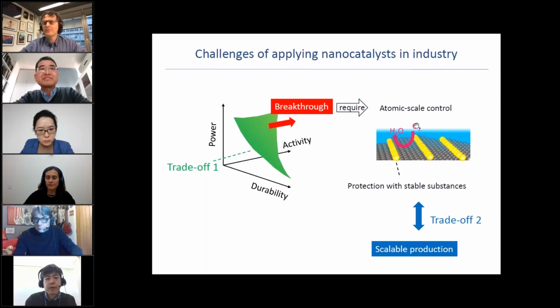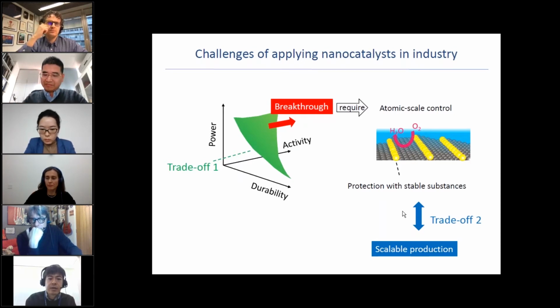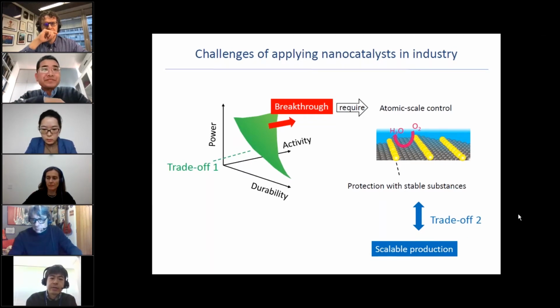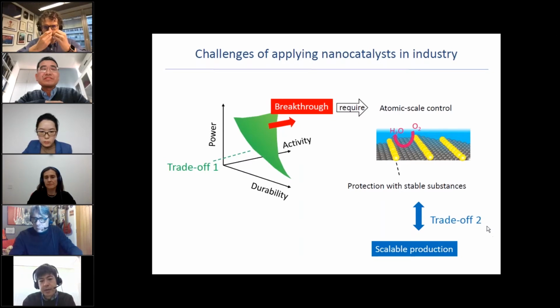So the requirement for high surface area poses an issue of durability, leading to trade-offs between the activity, durability, and power density, as shown by the green surface in the left figure. So for overcoming the technical issues, some new approaches are necessary, but we consider that this is possible. One example is site-selective surface modification of the catalyst surface with foreign stable materials, as shown in the right figure.